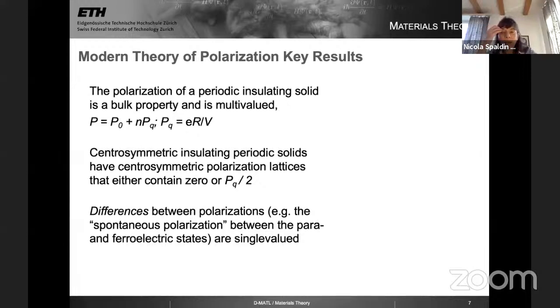And this all seemed a bit weird, except what was also noted was that differences between polarizations, for example the spontaneous polarization between a paraelectric centrosymmetric structure and its ferroelectric state, the measurable part of the ferroelectric polarization, are single valued. So there was actually no ambiguity between theory and experimental reality. So I very much recommend that you go read that last set of papers on our poll at the end.